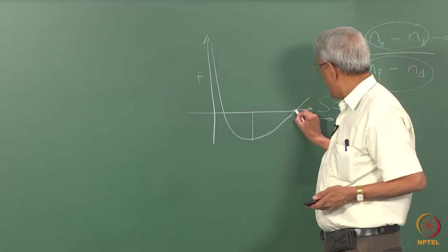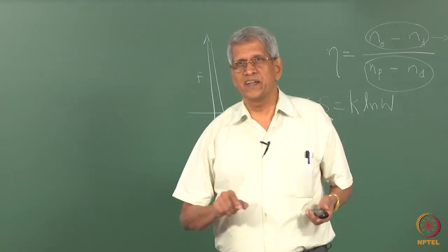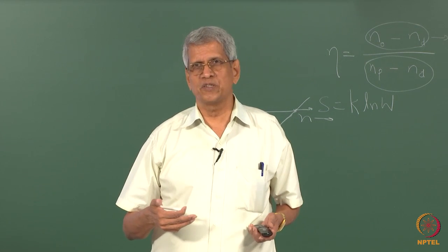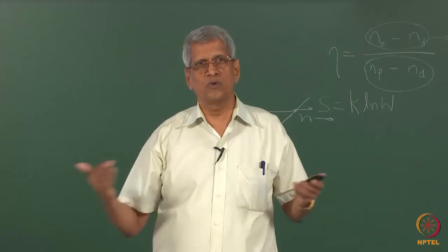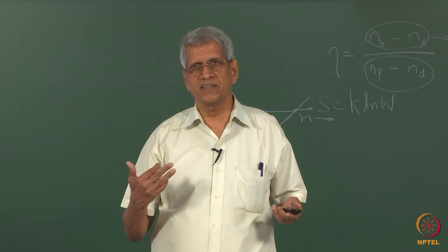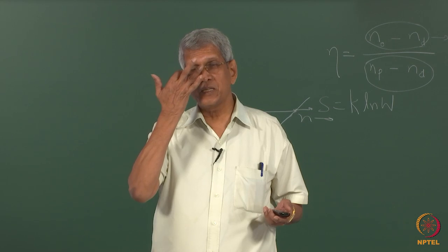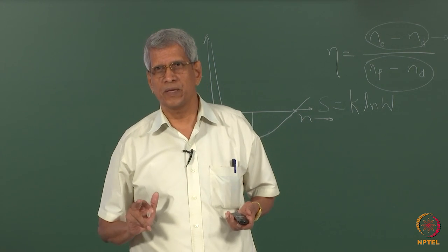Up to this point, this is the critical concentration at which, by adding one more vacancy into the system, the free energy becomes high. Now it is no longer in thermal equilibrium, correct? In all other cases the defect concentration is there, but it brings about a free energy reduction. One should keep this in mind.